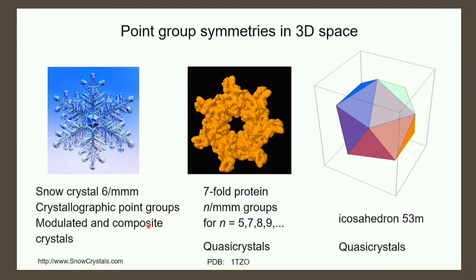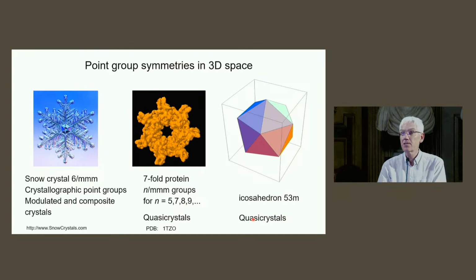Then, if we do not insist on long-range order, we have local order. For example, with proteins, we can have the 7-fold arrangement of 7 equal protein molecules. Very nice. This is a picture taken from the Protein Data Bank, an experimental crystal structure of a protein containing these 7 copies in a 7-fold order. And the mathematicians tell us there are, starting with 4/mmm and 6/mmm, actually n/mmm, an infinite number of these groups based on the highest symmetry rotation axis: 5-fold, 7-fold, 8-fold, 9-fold, 200-fold, whatever you like, and that's all.